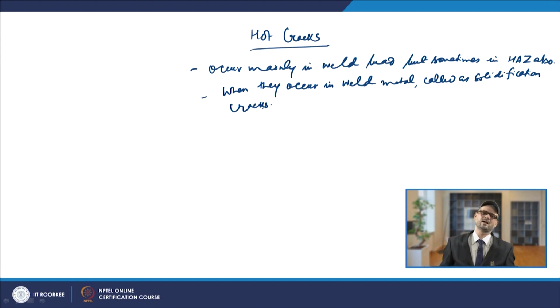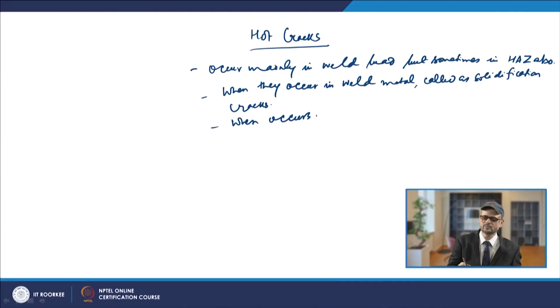But we will study these cracks more, because in the case of HAZ there will be a different kind of mechanism. You will have some phenomena occurring on the grain boundaries. You have the presence of low temperature eutectics. Because of that, these cracks are likely to occur, so they are known as liquation cracks. When it occurs in the HAZ, it is known as liquation cracking.